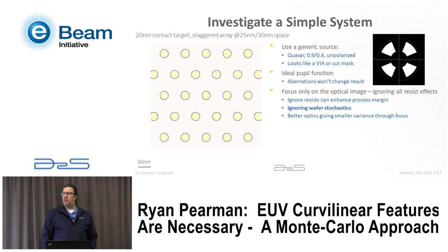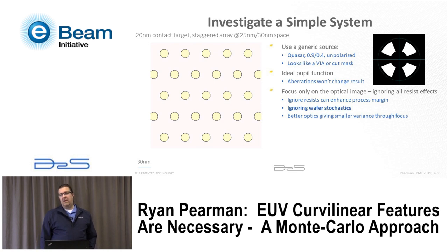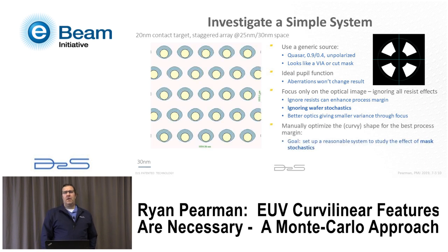We're not taking into account resist effects, although they're significant for EUV, and we're also not taking into account wafer stochastic effects. The assumption is that getting the best optical system, regardless of stochastics, is a necessary and sufficient condition. If you actually look at the optimal correction for this situation, it is a set of shifted ovals — which may not be what you'd have predicted but is actual reality. Since this is a simple system, we could manually optimize these curvilinear shapes.